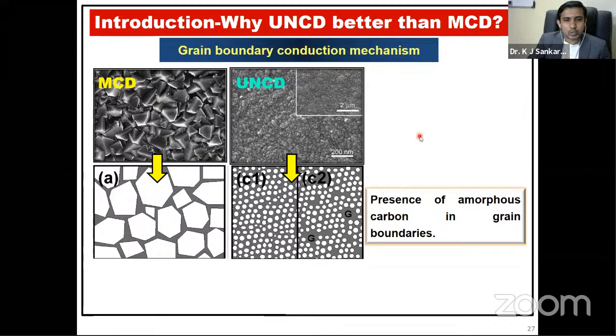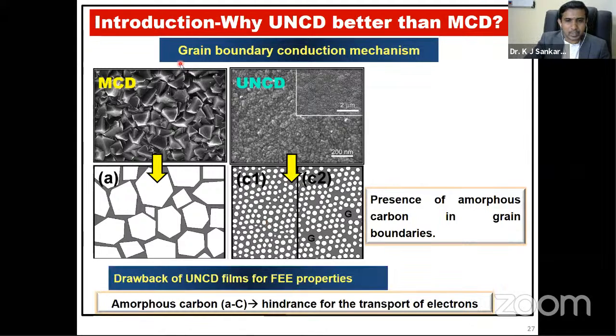So the transport of electrons and the supply of electrons from the bulk material from the bottom to the top portion is very easy if you have the amorphous carbon. But if you look at the MCD, there are bigger grains with less amorphous carbon, and an aspect ratio that is very low. But these are UNCD grains of spherical nature. It has the high aspect ratio, so that electron emission will be enhanced, which shows a very good current density. So UNCD is much better than the MCD because of the presence of amorphous carbon in the grain boundaries. So this mechanism is the grain boundary conduction mechanism.